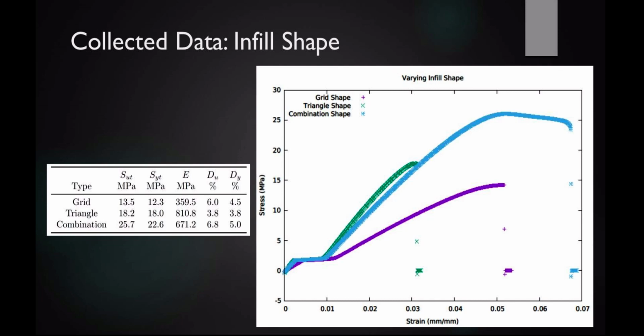The triangle shape has a high modulus, and it's likely because we're talking about 30, 60, 90 triangles, which can lock into place a bit more compared to the 45-degree angles and 90-degree angles of grid and combination. And then combination shows really what we would expect from most curves like that. So combination is great when you want all-around good properties, and that triangle is great when you want a really high Young's modulus.